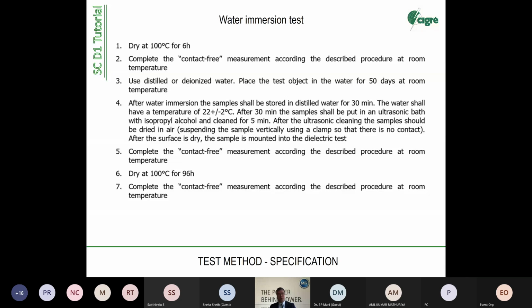So you can imagine, and there's also some limit. You can do this, for example, with eggs. If you increase the temperature, you can speed up the ageing. But if the temperature is too high, then your egg is boiled. So you don't see the original effect anymore. You get a change in effect. And this is why we limited it to 50 degrees, because we know that most polymeric materials do not change the aging mechanisms in this range. Above 50 degrees, there may be a change in the aging mechanisms that we do not simulate in the right ways.